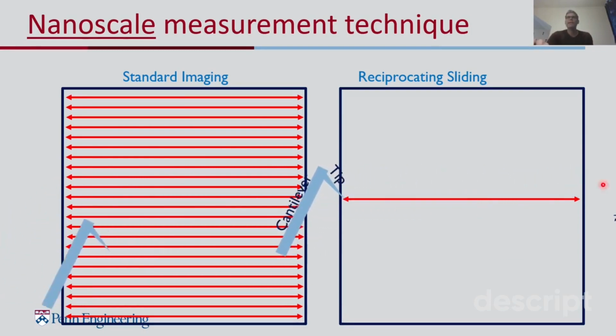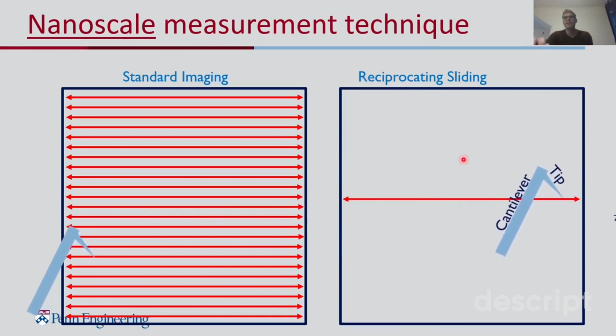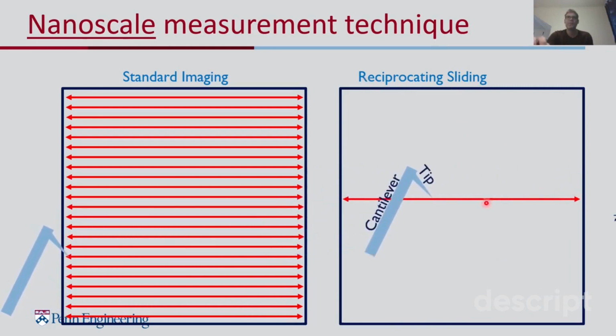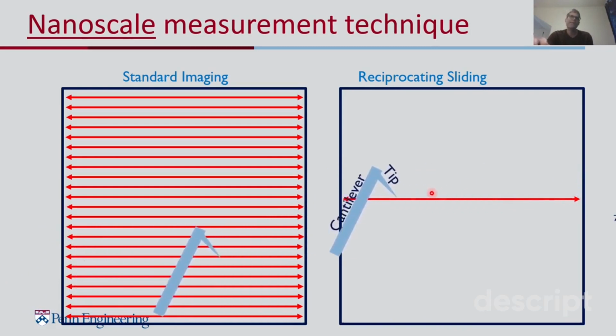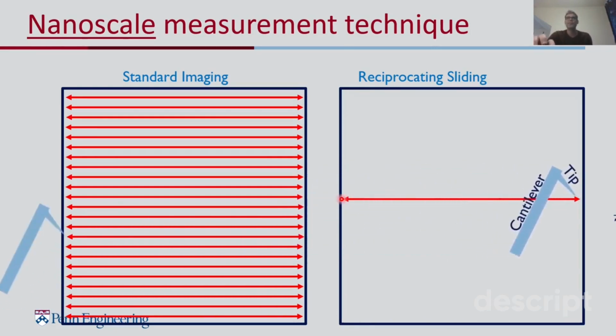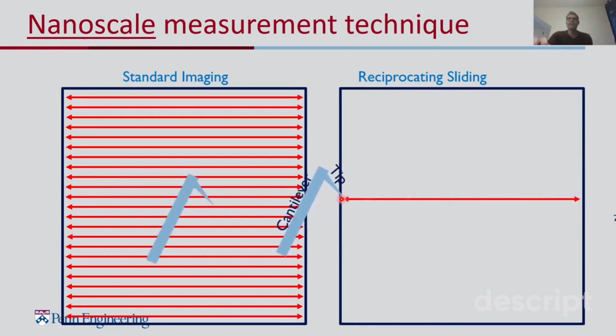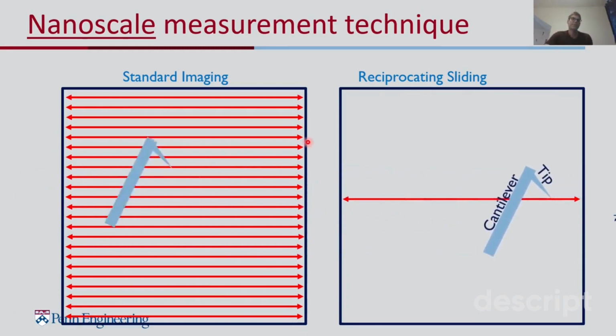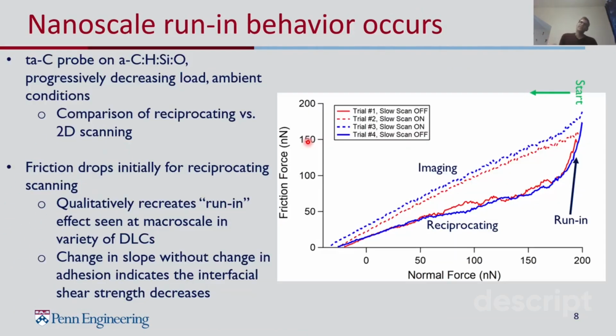And then the other way of making these measurements is what's referred to as reciprocating sliding. So we just slide back and forth just like a tribometer does. And so there will be some evolution in the friction response that's due to transformation or wear of the underlying sample. And so comparing these two can be useful, as I'll show in this slide. On this slide, we have a nanoscale friction result. This was done with an AFM probe that was coated with tetrahedral amorphous carbon. So that's just another diamond-like carbon that's very highly sp3 and low in hydrogen. And this is useful because it has a similar magnitude of hardness to diamond. And what that means is that it's very stable against geometry changes.